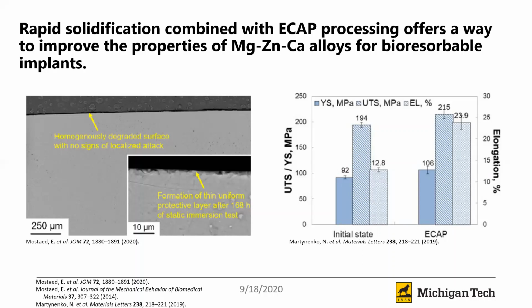So as you can see here, rapid solidification of a magnesium, zinc, calcium alloy greatly improved the corrosion resistance and corrosion behavior of the alloy, where you can see that there's no localized pitting or cracking. And this is due to the rapid solidification process trapping atoms within the solution instead of allowing them to precipitate out, eliminating the presence of these precipitates.